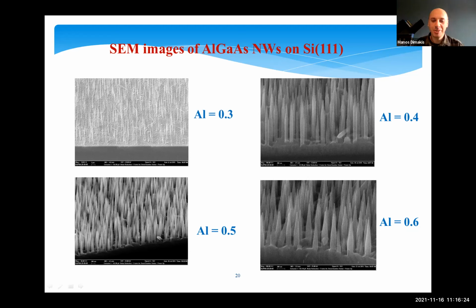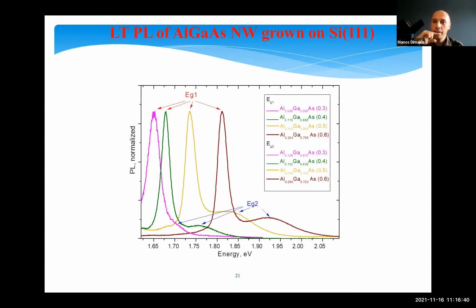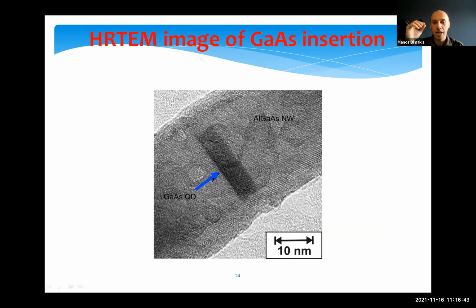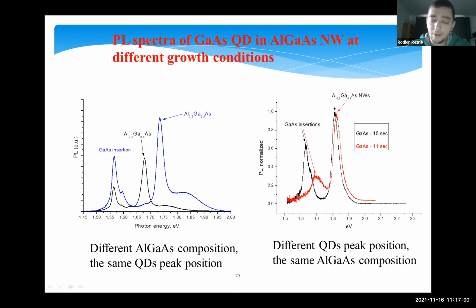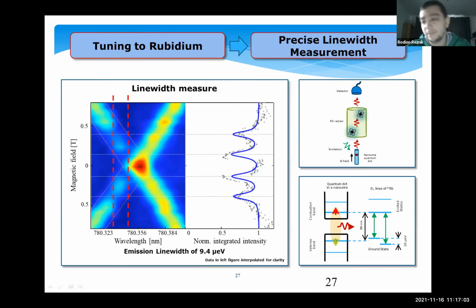Yes, thank you very much. It was a very nice talk and very rich in results. I have two questions, if I can. One is, have you quantified the sharpness of the interfaces in your gallium arsenide quantum dot inside the AlGaAs nanowire? From the TEM it looks nice, of course, but do you have a... It's not easy to do it because of the small contrast between gallium arsenide and aluminum gallium arsenide materials. So we can say this only from our sharp lines.